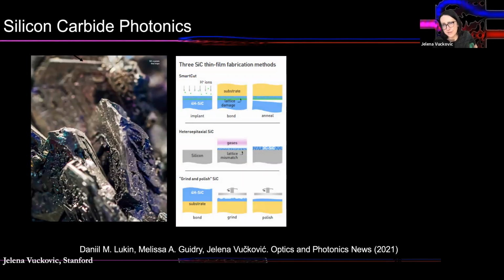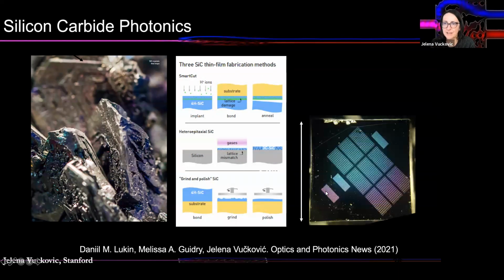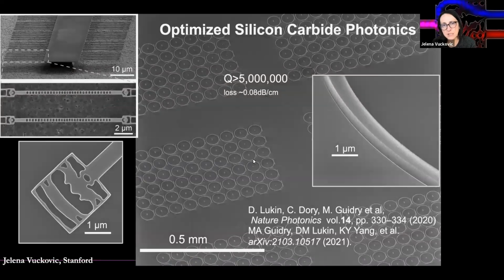And in silicon carbide, it's the same story, but of course, when you start from bulk silicon carbide, you either do three-dimensional bulk carving, which we tried, but then we also came up with another idea that works even better for silicon carbide, which is to bond silicon carbide on oxidized silicon, grind thin until you obtain a thin film, and then use that thin film silicon carbide to make your photonics. So it's really a grind and polish method, which brings you from here to a chip that works really well, something like this. And with that, we can also build very high quality photonics, with quality factors of resonances greater than 5 million. Loss, this is in telecommunication units, but it's actually comparable to the lowest loss photonic structures made in foundries for silicon nitride. And we can also have inverse design structures and color centers inside and build scalable systems.